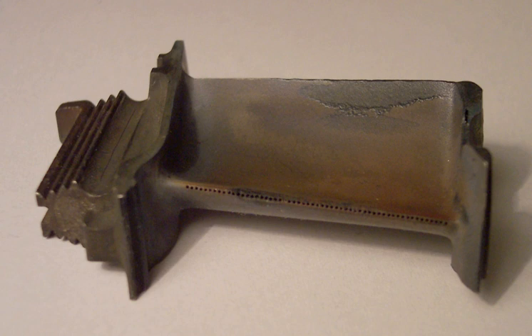Re has also been shown to promote the formation of rafts of the gamma prime phase as opposed to cuboidal precipitates. The presence of rafts can decrease creep rate in the power law regime controlled by dislocation climb, but can also potentially increase the creep rate if the dominant mechanism is particle shearing. Furthermore, Re tends to promote the formation of brittle TCP phases, which has led to the strategy of reducing Co, W, Mo, and particularly Cr. Younger generations of Ni-based superalloys have significantly reduced Cr content for this reason, however with the reduction in Cr comes a reduction in oxidation resistance. Advanced coating techniques are now used to offset the loss of oxidation resistance accompanying the decreased Cr contents.